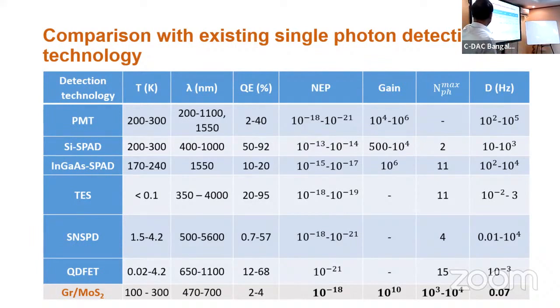The silicon SPADs are 10 to the power minus 13. The InGaAs is about 10 to the power minus 17. The superconducting ones are obviously low temperature, so they will be low noise. They are about the same order, 10 to the power minus 18. The TES is 10 to the power minus 18 as well, while SNSPDs are 10 to the power minus 18 to minus 21.